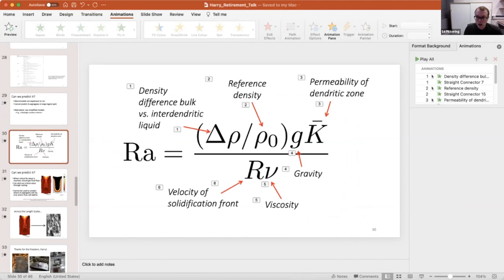And also you could play around a little bit within the spec of the alloy chemistry to make sure that this density difference is as low as possible. So for instance, you could pick the lowest carbon and silicon levels that you can get your hands on and increase the moly levels. And maybe you might get to a point where you haven't got the same driving force for fluid flow. And there are indications that in some steel grades, the interdendritic liquid sinks because it's more molybdenum rich. You don't have any of this horrible segregation, or at least as much of it. So yes, you can design it out as well.